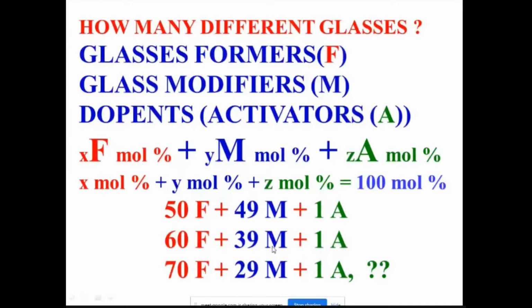For example, to get total internal reflection in fiber optics, you are going to change only 1% of refractive index. So 1% of refractive index can be easily changed, not by changing 1 gram. I can change 0.5 gram, or I can change 0.5 milligram. So you have the technology, you have a machine in such a way, you can measure the materials in milligrams or nanograms. So keep on changing the molecular composition, stoichiometric ratio. You can prepare infinite number of glasses only by changing the former, modifier, and activator.